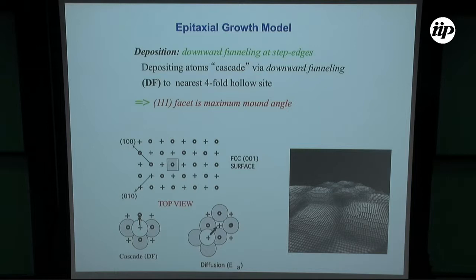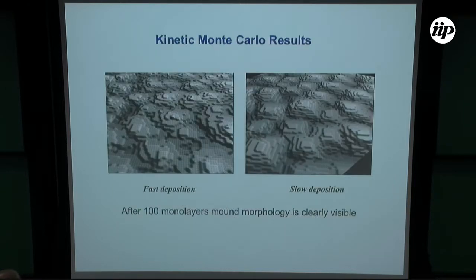So what we did was we looked at this (001) surface. So there are both 4-fold hollows, and there are atoms that are sitting in a layer below. And to model this diffusion, atoms can hop from one 4-fold hollow to another one. And if an atom is sitting at the step edge, it goes from the upper layer, kind of incomplete 4-fold hollow, to another 4-fold hollow point in the lower level. The maximum facet you can have is a 1-1-1 facet in this kind of structure. And so you can do the Monte Carlo simulation with this kind of more realistic